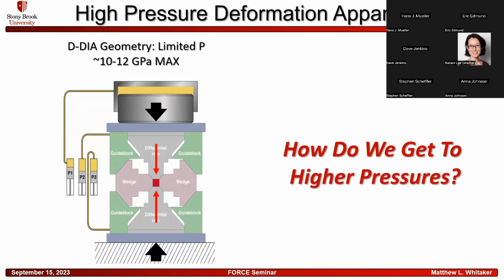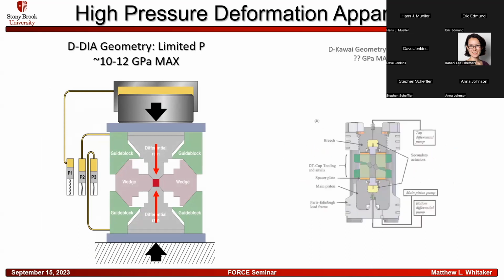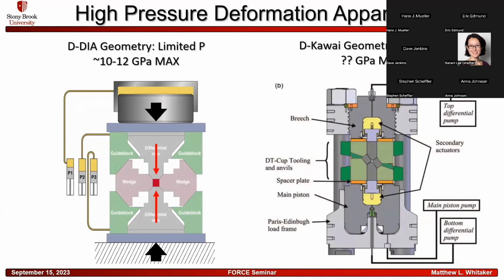So how do we get to higher pressures? And that's where the deformation-Kawai geometry comes into play. We can definitely reach higher pressures with that, but what is the maximum pressure that we can achieve in these types of experiments? That's something that we set out to understand. Very similarly to the D-DIA, we have the pressure come in from below, where we have the entire guide block squeezed together to add pressure to the sample, and then we can drive the top and bottom pistons separately in order to deform it. And that's basically how this system works.